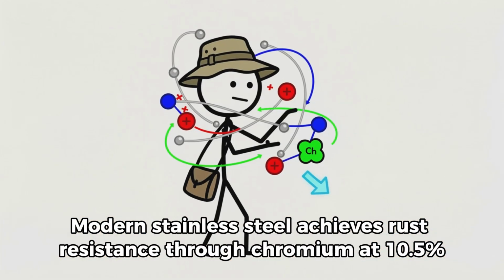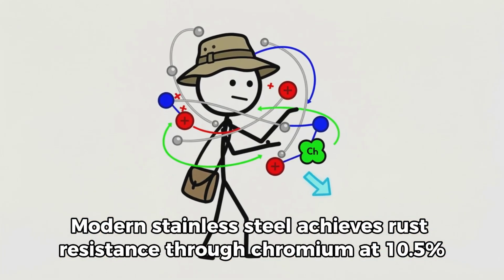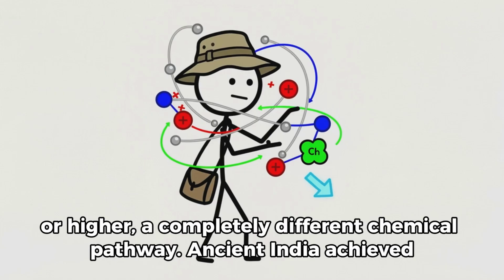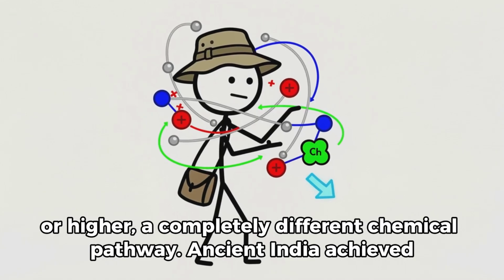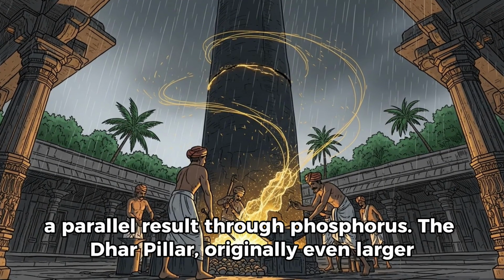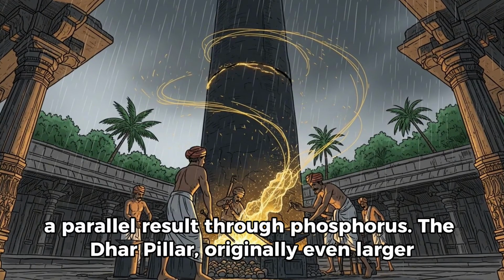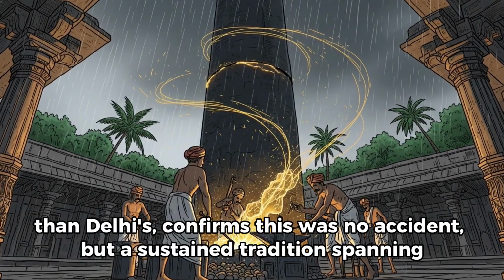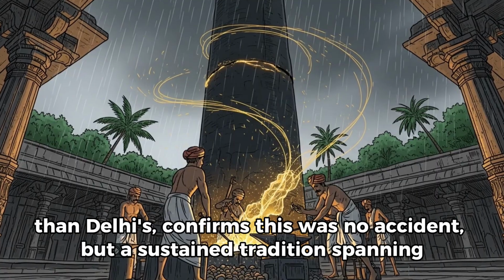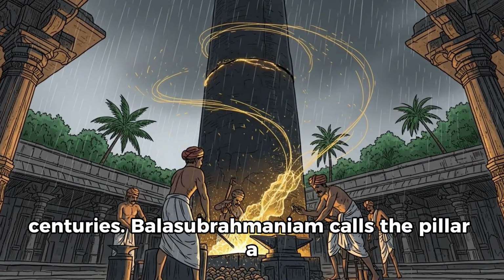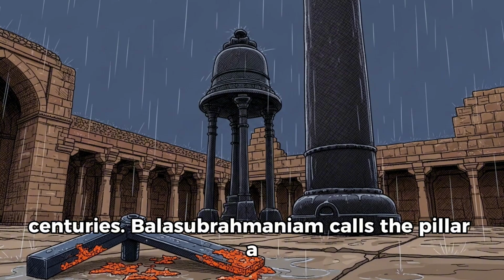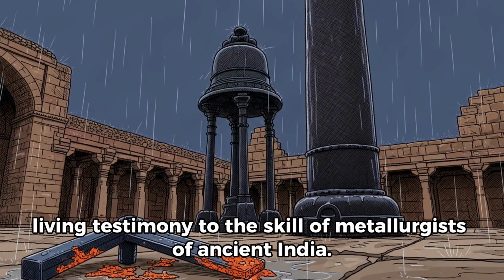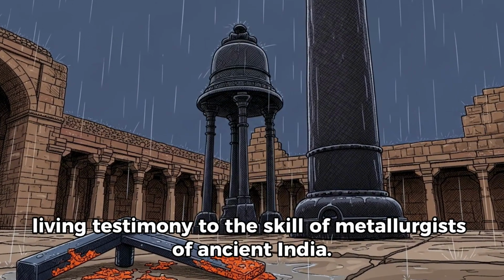Modern stainless steel achieves rust resistance through chromium at 10.5% or higher, a completely different chemical pathway. Ancient India achieved a parallel result through phosphorus. The Dhar Pillar, originally even larger than Delhi's, confirms this was no accident but a sustained tradition spanning centuries. Balasubramaniam calls the pillar a living testimony to the skill of metallurgists of ancient India.